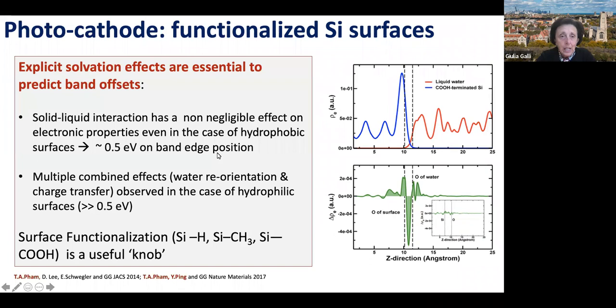For silicon, explicit solvation effects are essential to predict band offset. Even for hydrophobic surfaces, and this is why I'm showing this charge transfer, which is small but important, the presence of explicit solvent gives you a change in the bands of around 0.5 eV. So it's very important.